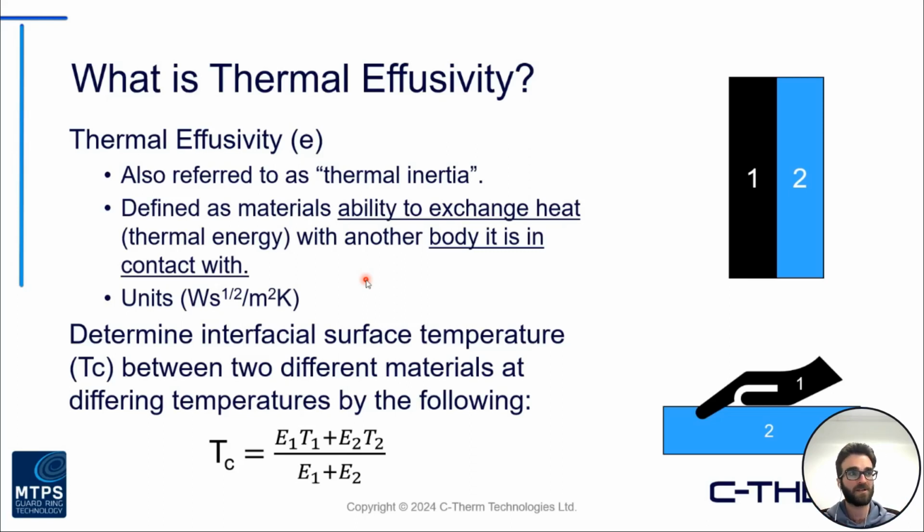One of the other applications that we've seen is the perception related to the temperature change that occurs between the interfaces upon touch. Like if you take the human hand and touch a material, different materials will of course feel quite differently. Some extremes are something quite low in effusivity, something insulative, compared to the other extreme, like a metal.